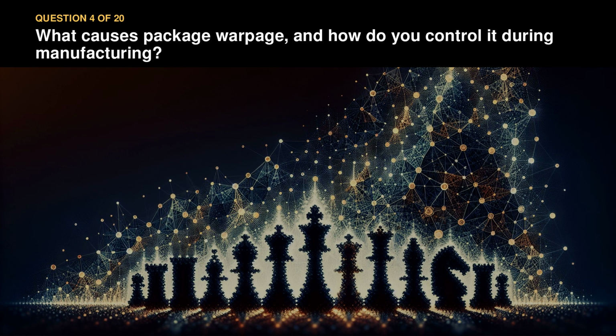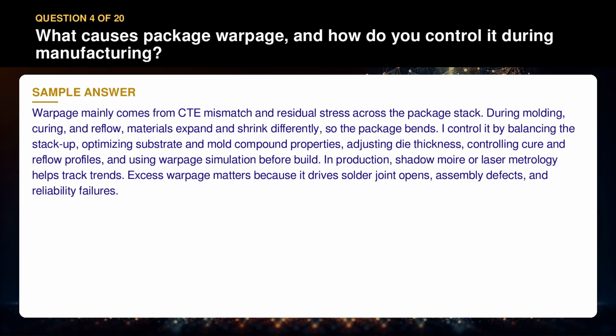Question 4. What causes package warpage and how do you control it during manufacturing? Warpage mainly comes from CTE mismatch and residual stress across the package stack. During molding, curing, and reflow, materials expand and shrink differently, so the package bends. I control it by balancing the stack up, optimizing substrate and mold compound properties, adjusting die thickness, controlling cure and reflow profiles, and using warpage simulation before build. In production, shadow moire or laser metrology helps track trends. Excess warpage matters because it drives solder joint opens, assembly defects, and reliability failures.